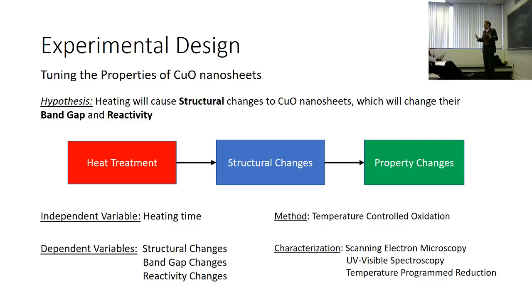I just heated it up a little bit. I knew how to measure band gap, and I had a reactor, so I could measure reactivity. My hypothesis was that heating will cause some structural changes, and these changes will cause changes in the band gap and the reactivity. I was going to heat to not-so-hot temperature. I didn't want to kill the structure, so I heated to 350 Celsius, in between 300 where nothing happened and 450 where too much happened.